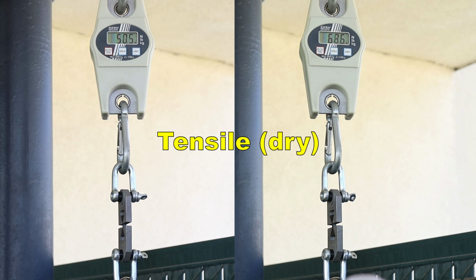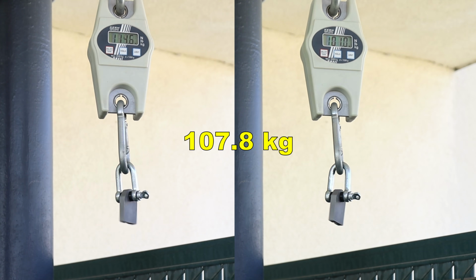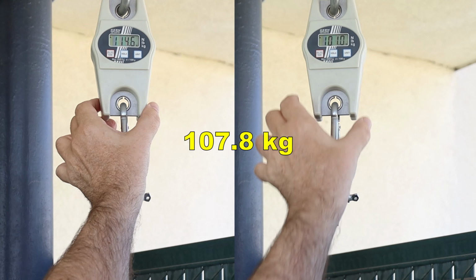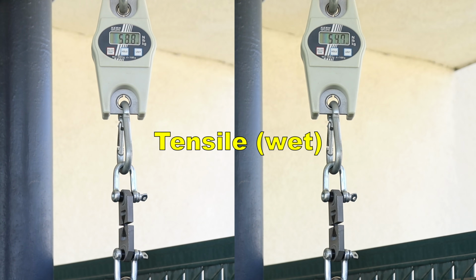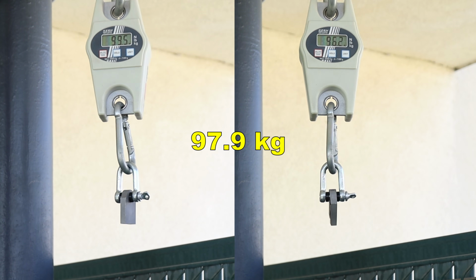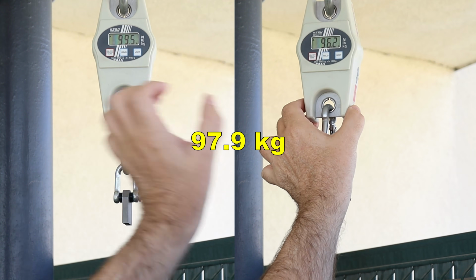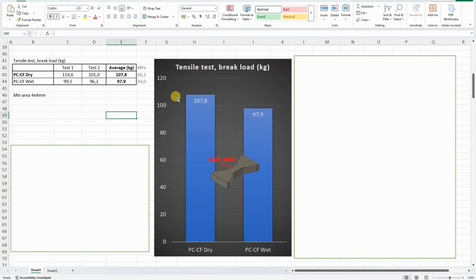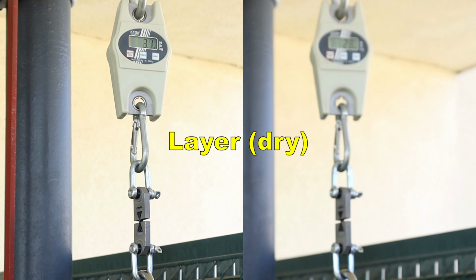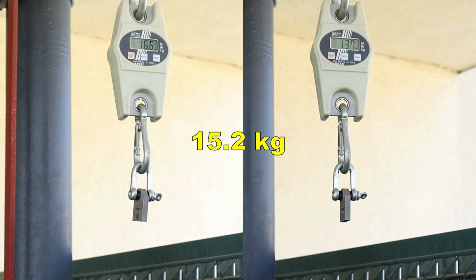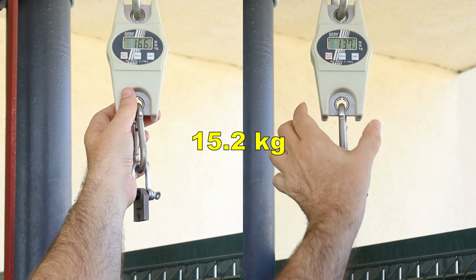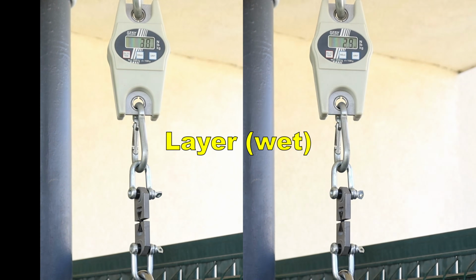Tensile test, horizontally printed objects. This was with dry filament, and now wet. A small advantage: objects printed from dry filament are stronger by approximately 10%. Layer adhesion, vertically printed objects. And now wet.